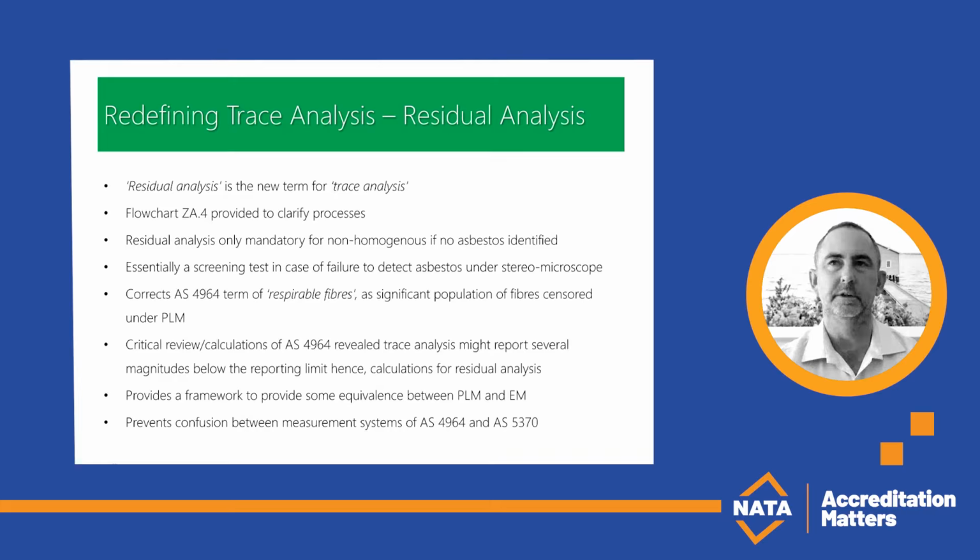The process is repeated with another slide, and if 2 slides yield concordant results, either above or below the reporting limit, the result is then reported accordingly. In cases of discordance, a 3rd slide is prepared and the result is based on the 2 concordant slides. The procedure is the same as in AS 4964, however, it incorporates a crude point counting criterion.